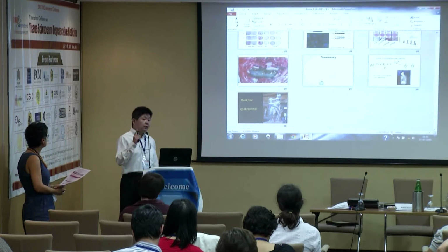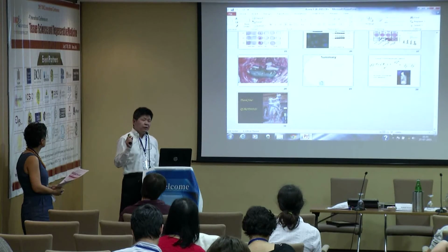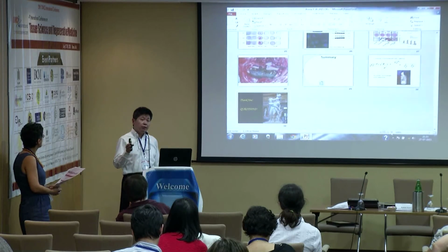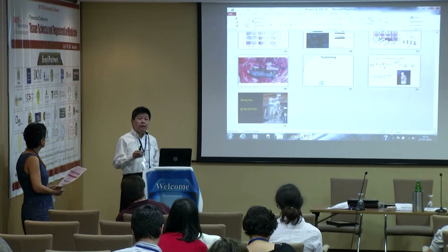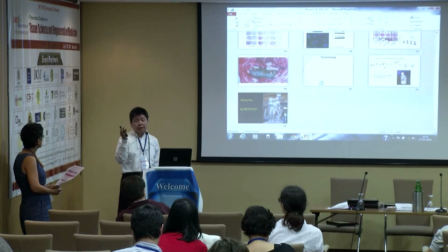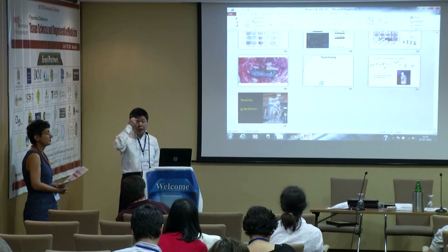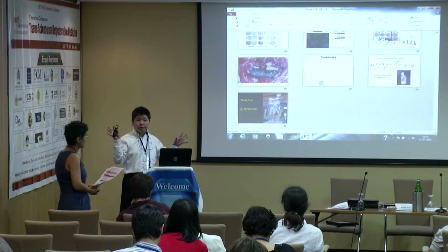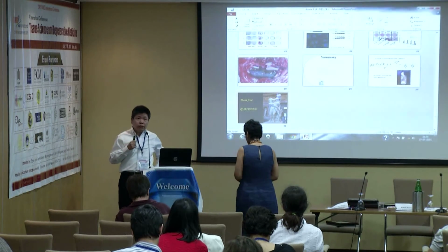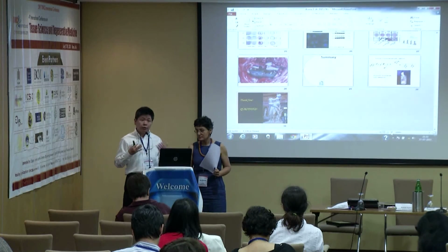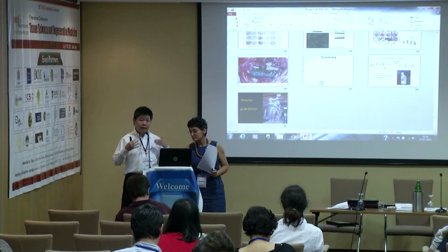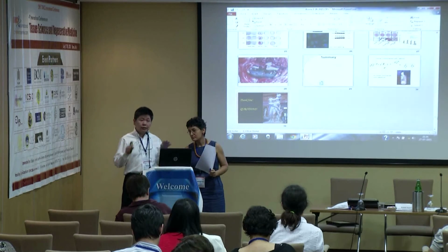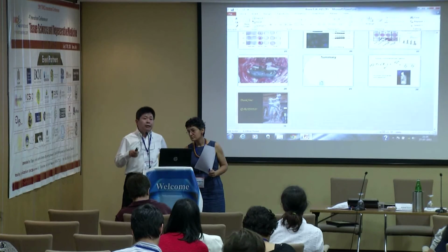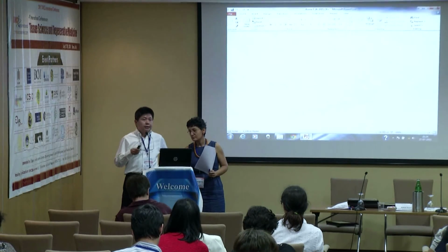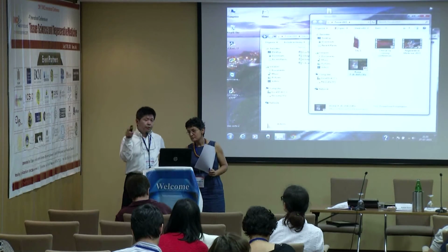Thank you, that's a very good question. We are still looking at the leaching study, and we have very little data on that. The leaching components are at the micromolar level, and that's why you see our cell testing is at the micromolar level. Most of the dopamine has been converted into polydopamine in the system. Once it's converted to polydopamine, it no longer has the dopamine effect. However, quite a few articles have been published mentioning that polydopamine also increases cell adhesion. It can increase the integrin reaction with the cells, so that's another advantage of polydopamine. Yes, but they instead provide the adhesion.